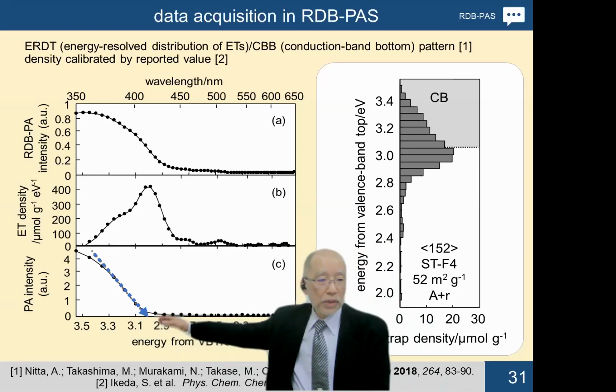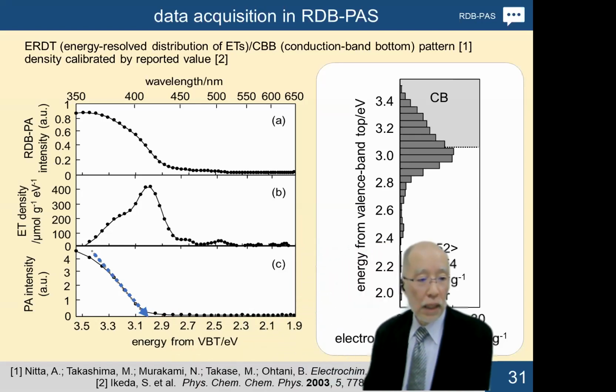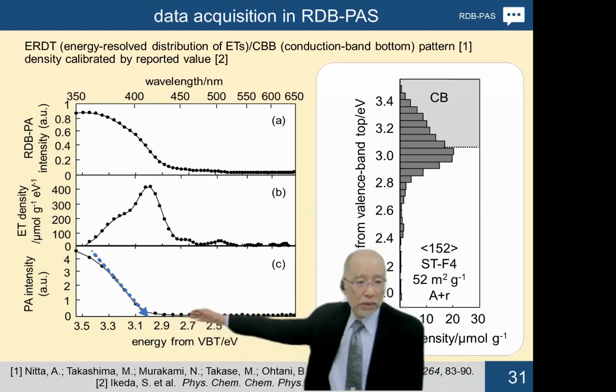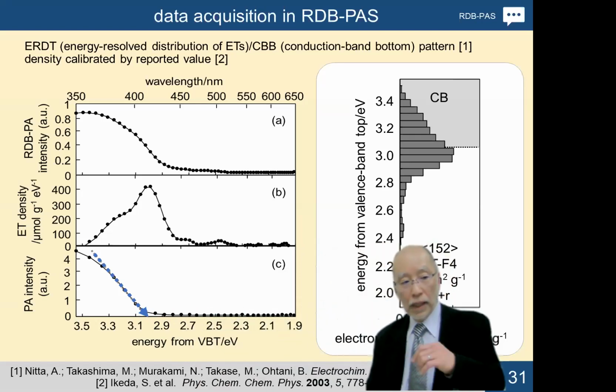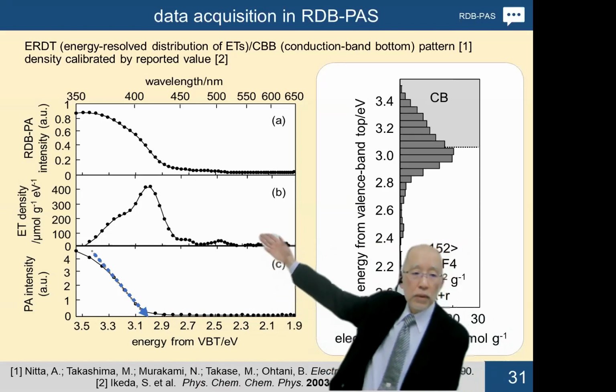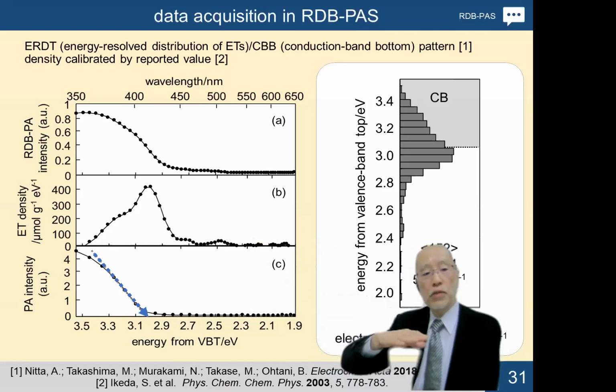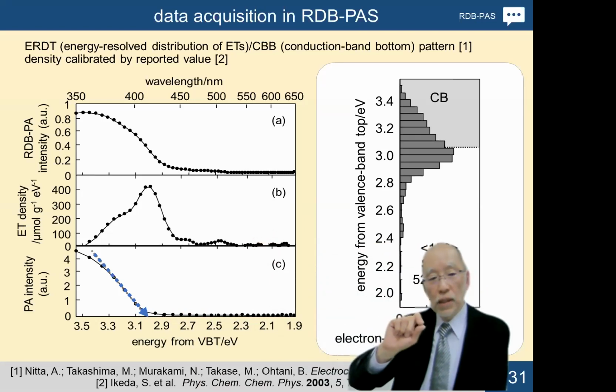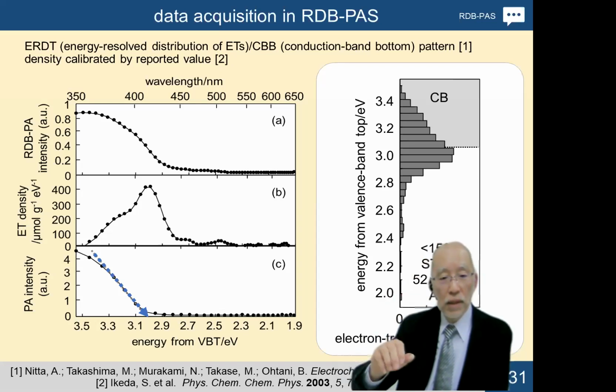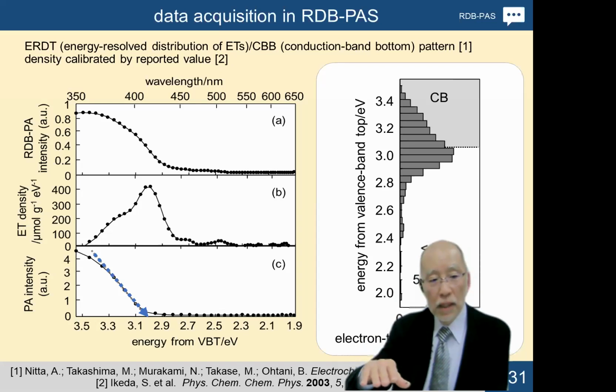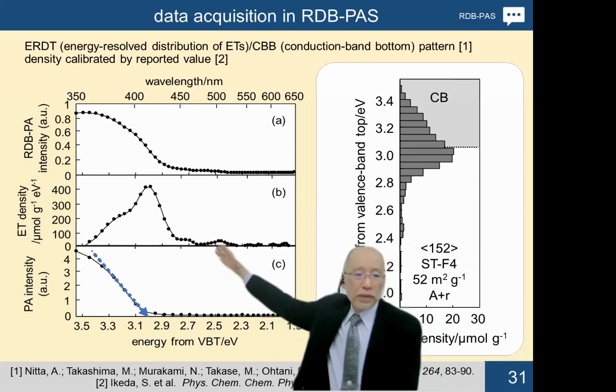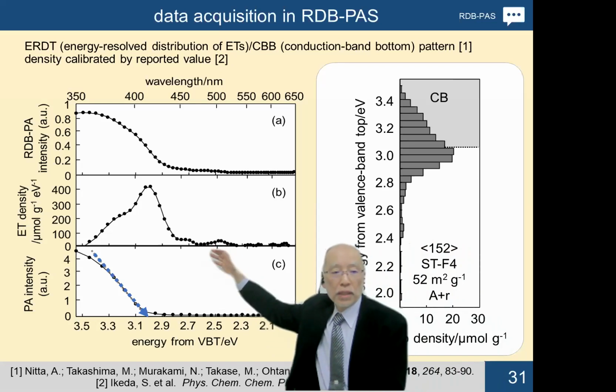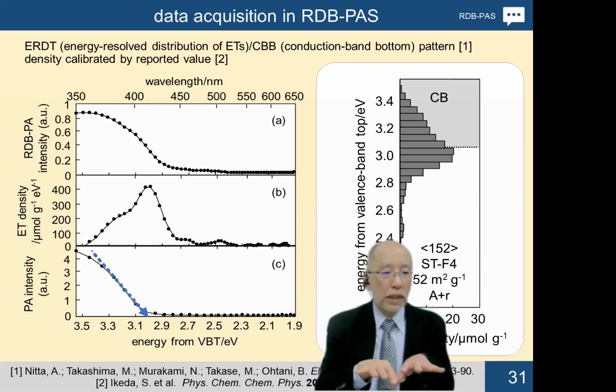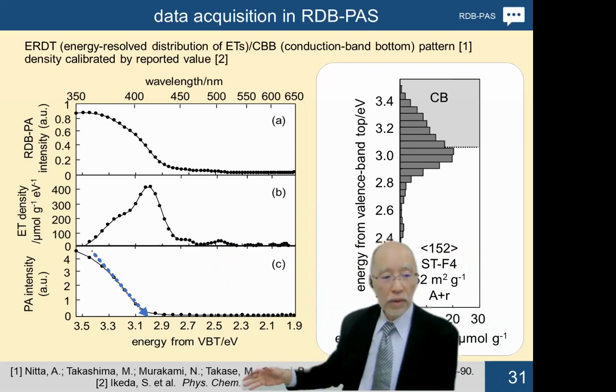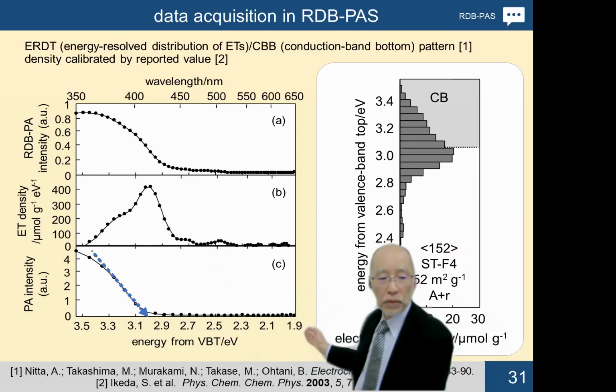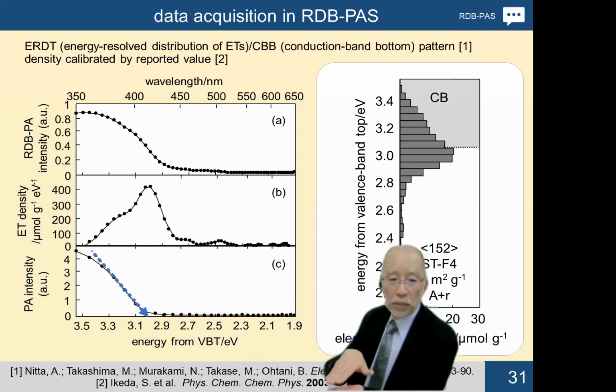Here, that is about 3.0. So that means about 400 nanometer. That is about 3.0 electron volt band gap. And as I told you, the excitation to electron trap happens from valence band. And the lowest energy required for excitation is from valence band top position. So therefore, in practice, this energy is shown in difference to valence band top position. So here, 1.9 electron volt means from the valence band top position.